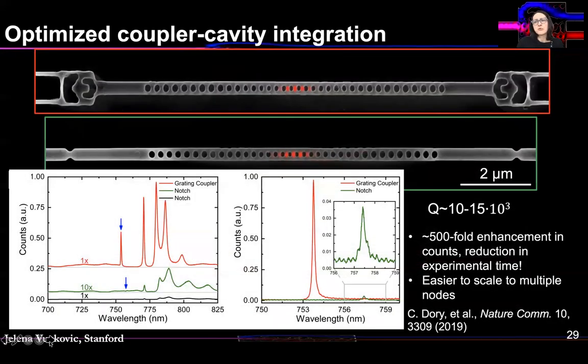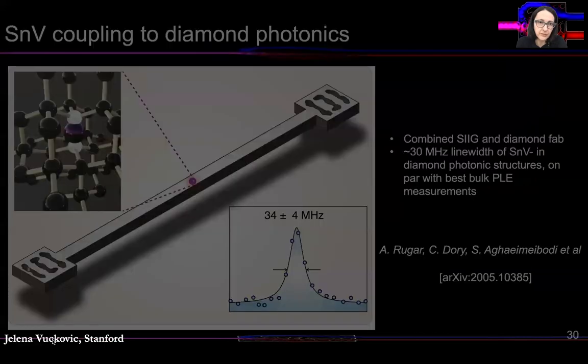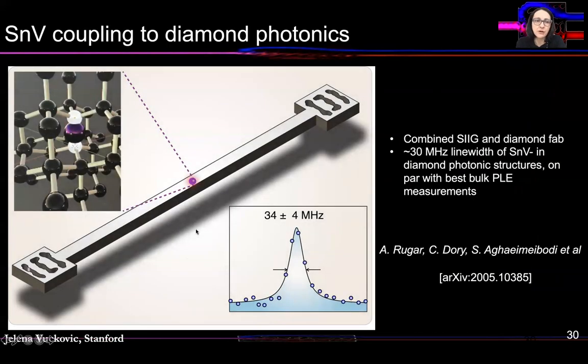This leads to tremendous improvements in the properties of your diamond circuits, which I'll illustrate here with a very simple example of couplers. If you're looking at transmission through a resonator, using simple notch couplers with 1% efficiency, you have to integrate for 10 seconds and you barely start seeing some signatures of the cavity. If you optimize the couplers, with very simple designs of the same footprint, you can achieve 30% efficiency. After only 1 second of integration, you are already seeing a very strong signal from the cavity. So you have a 500-fold enhancement in counts and a dramatic reduction in experimental time, which would allow you to scale this further to a large number of nodes and circuits. We are now combining this with color centers, primarily tin vacancies.